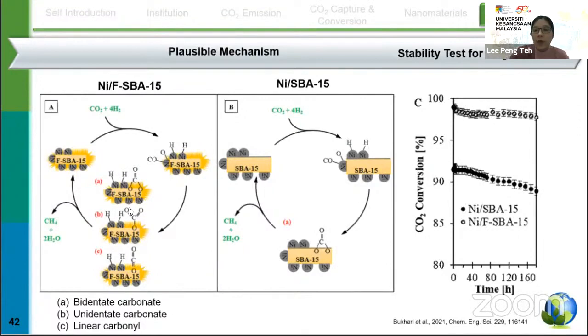In the nickel fibrous SBA-15, we have three types of intermediate species: a bidentate carbonate, a unidentate carbonate, and a linear carbonyl. So this is the bidentate carbonate, this is the unidentate, then we have a linear carbonyl. While for the nickel SBA-15, we only observe the bidentate carbonate present as the intermediate species. This mechanism, basically, we are using in situ FTIR to study the whole process.